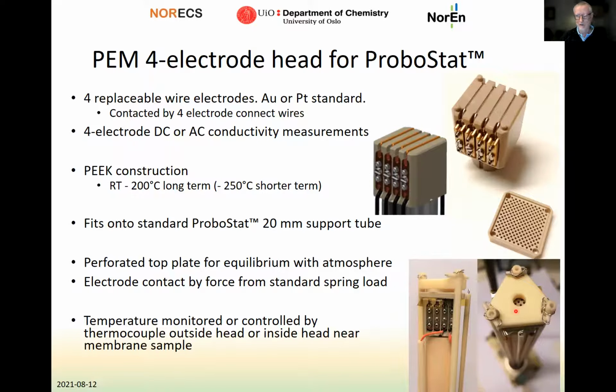The temperature can be controlled or monitored using a thermocouple here on the outside of the head. But there is also a hole into most of the head on the inside, where also the inner thermocouple of the ProboStat can monitor temperature very close to the membrane itself. It stops just under here.